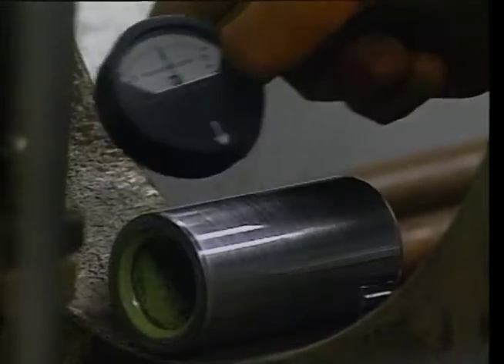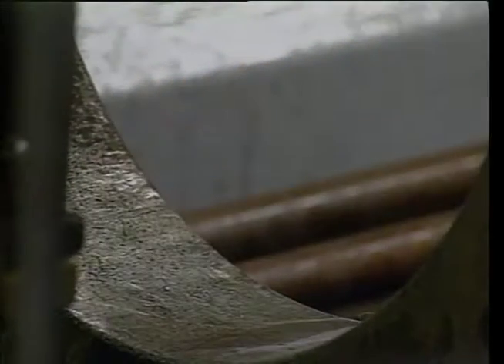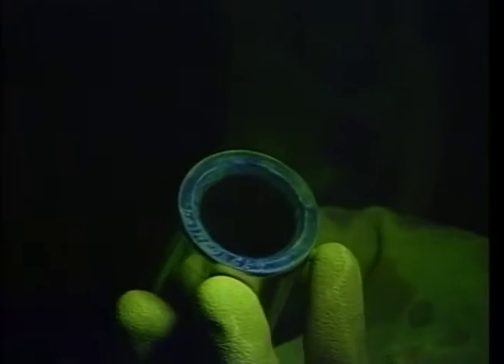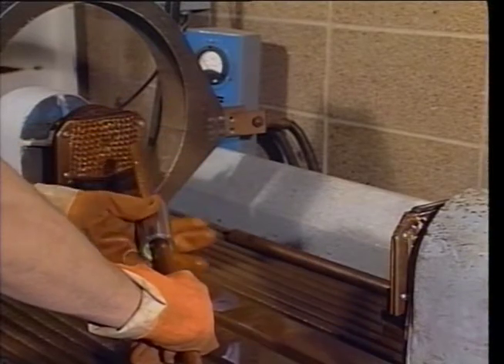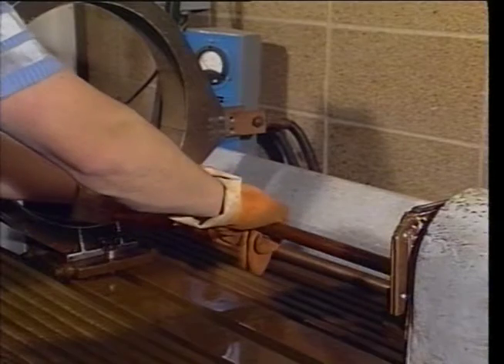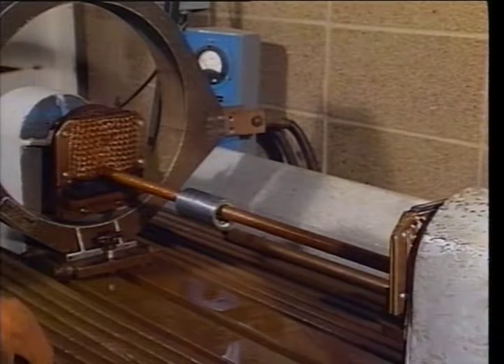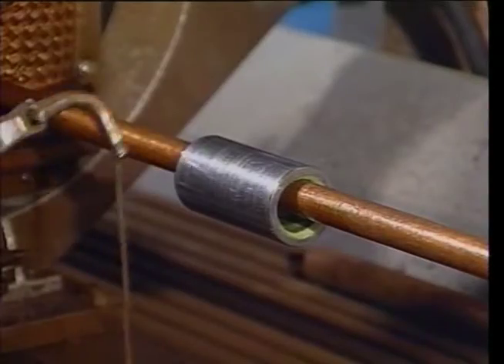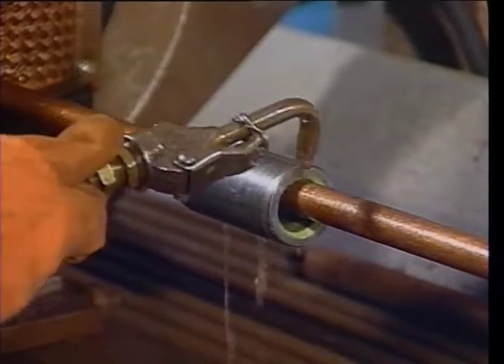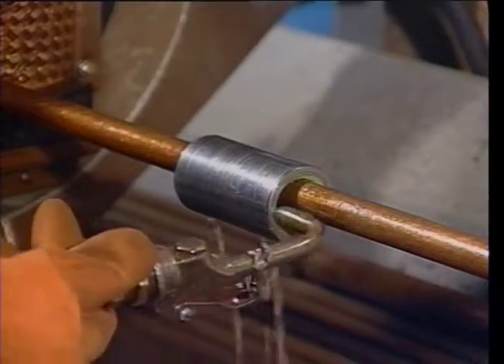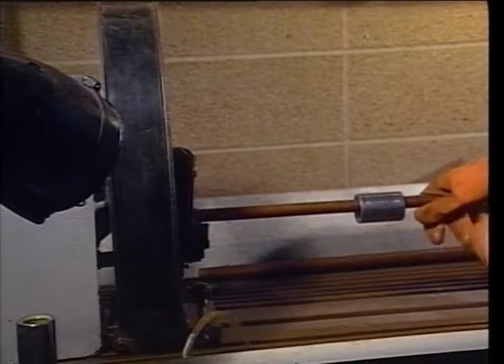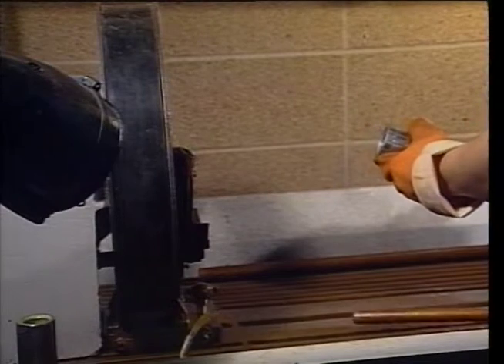The flux meter confirms the presence and direction of the magnetic lines of force. Then, under black light, the fuse pin is inspected for any discontinuity in these lines of force, an obvious indication of a flaw near the surface. In order to locate a defect, it is essential that the force lines pass approximately perpendicular to the flaw. Therefore, it's important to reapply the magnetism at right angles to the initial pass.